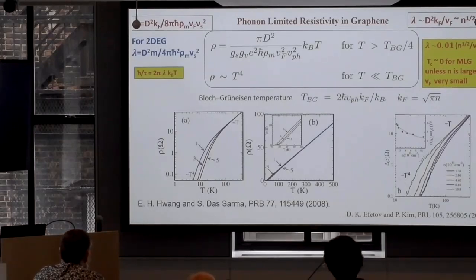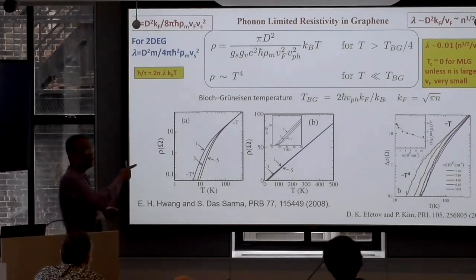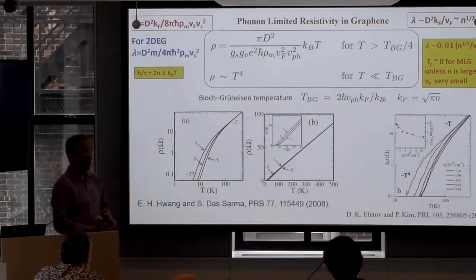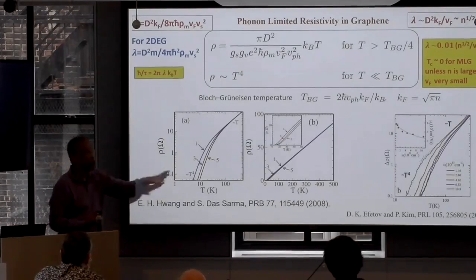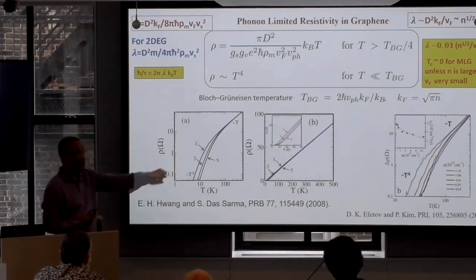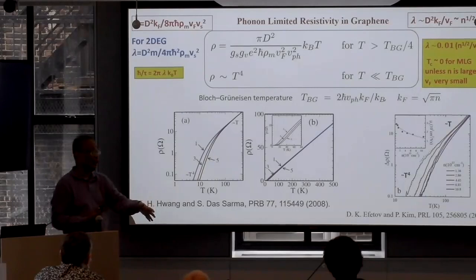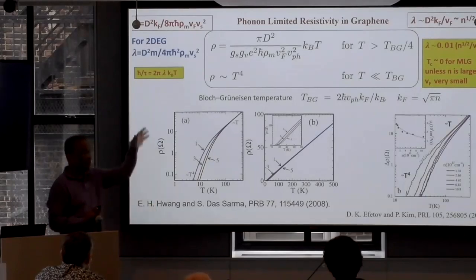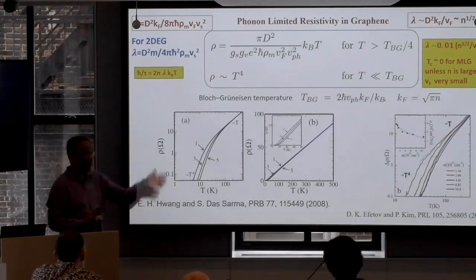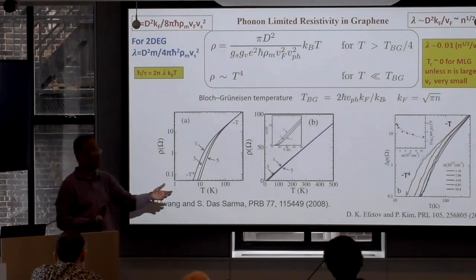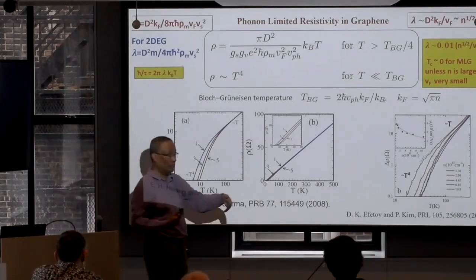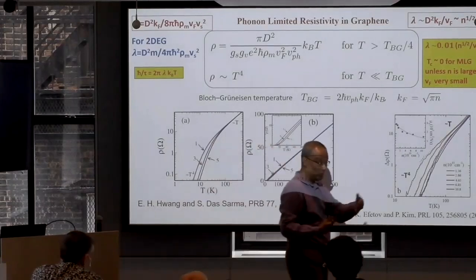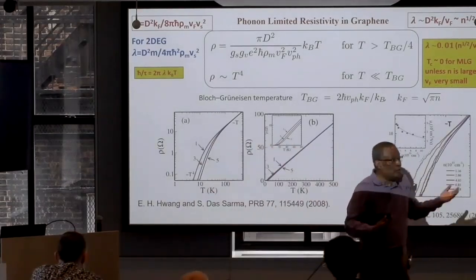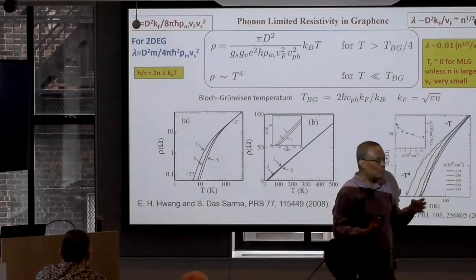Very good question. These are of course things I have studied at great length. It just so happens that this is after graphene has already become very, very clean. So I don't remember the residual resistivity, but it's minuscule. So this issue doesn't apply here, but this is very important in semiconductors. And by the way, this interplay can give you all kinds of non-monotonicity. We have many papers doing that, and these things have been seen in holes in gallium arsenide and so on, because there could be linear in T dependence coming from disorder, and these things in gallium arsenide are reasonably well established.